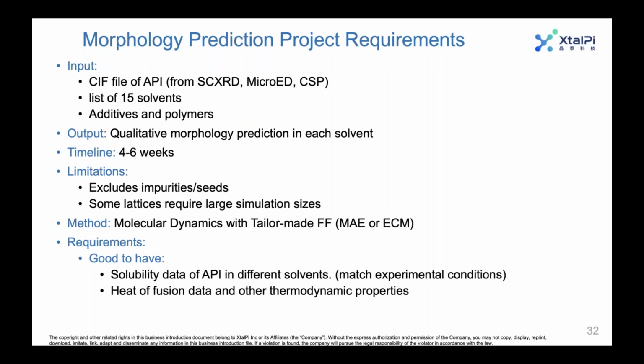The output is the qualitative morphology prediction in each solvent, or more specifically, each experimental condition that we simulate, and also the morphology landscape. The timeline, again, is 4 to 6 weeks. And some limitations, so this is a thermodynamic model, right, that I've shown here. There's no kinetics involved, so we can't simulate the effect that seeds might have on crystallization. And in terms of impurities, we've never done a project with impurities on the crystal faces. You can imagine that maybe the MD simulations would be sensitive to that. It's something we could potentially explore.